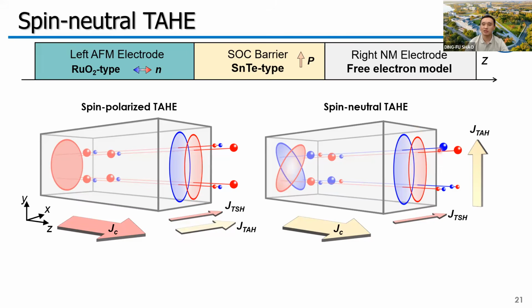We find that in the top half, the spins are matched for the barrier and the electrode. Then we have a large transmission. But for the bottom half, the mismatch of the spin polarization for the barrier and the electrode leads to a small transmission. This generates an unbalanced transmission along the y direction, which will result in a large anomalous Hall current.